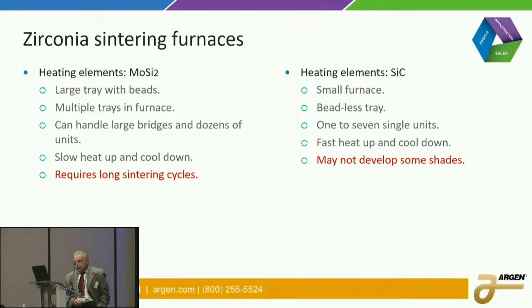Now, there's 2 types of heating elements. There's molybdenum disilicide. This is the traditional heating element. And then, in order to go faster, some manufacturers have introduced these heating elements with silicon carbide. And these are generally smaller furnaces because, again, you have to heat the furnace at the same time you're heating the work, right? And with silicon carbide, they put out a lot of energy fast, but it's not a lot of heat flux. So it can't heat up a big furnace.